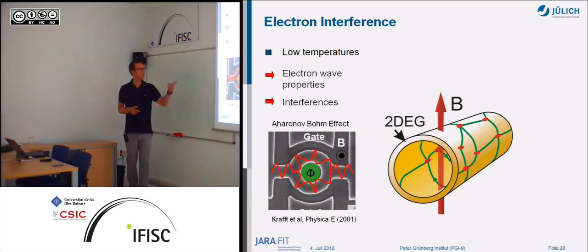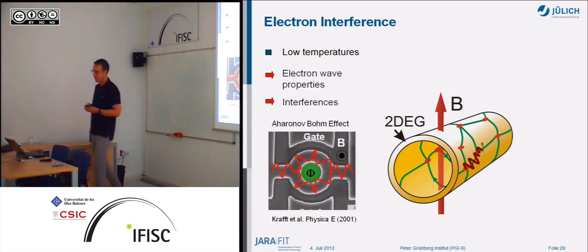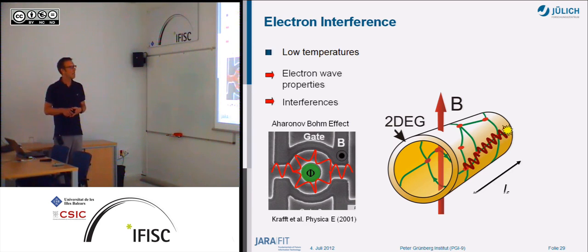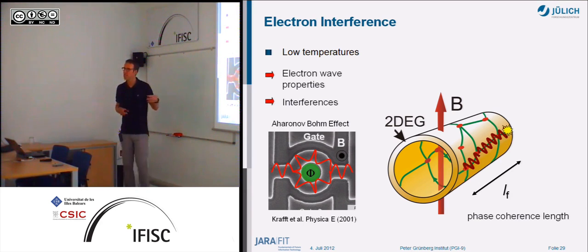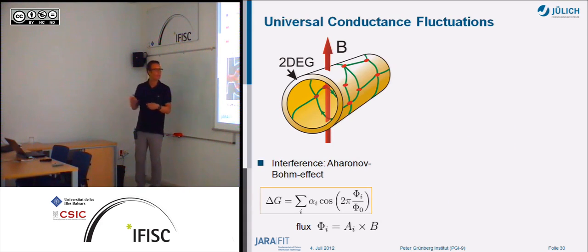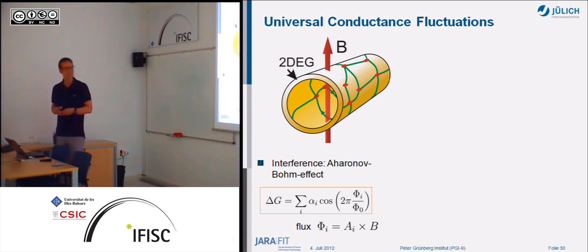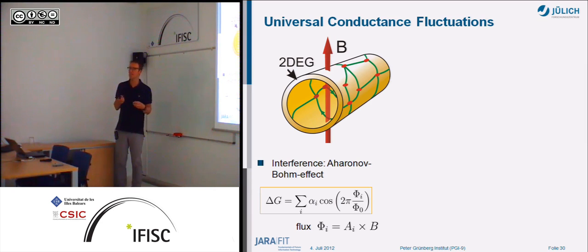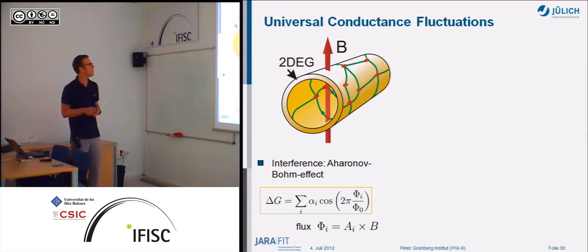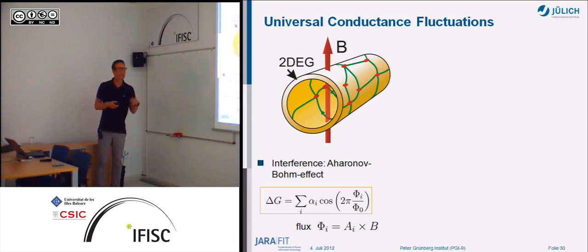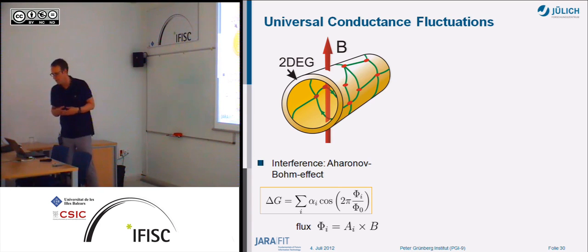This phenomenon, in principle, can also be seen in nanowires. If you think of a nanowire having some scattering centers here, then you also have some phase coherent transport, and the question is, what is the phase coherence length here? What is the maximum length where you can keep the phase coherence in the nanowires? And that's what we like to study, and we do that by studying the universal conductance fluctuations. This is a very interesting method to get information on the phase coherence, because the nanowire is a small structure, and you have a finite number of scattering centers here. So in the transport you see a fingerprint, so each nanowire behaves differently, and what you see in the transport is some conductance fluctuations.